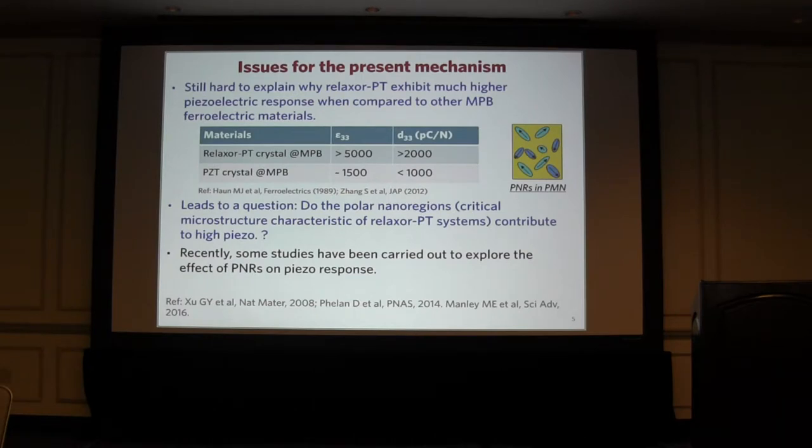But this mechanism cannot answer the question why relaxor-PT crystal exhibits very high piezoelectric response compared to other MPB materials. Because for the PZT ceramic, we can see from this figure, d33 and the dielectric permittivity are much lower than those of the relaxor-PT crystal. So we generally ask ourselves, do polar nanoregions, we call them PNR, contribute to the high piezoelectric response? Actually, recently, lots of studies have been carried out to explore this issue. Here I list a few of them as a reference.